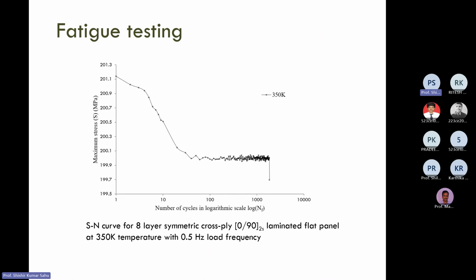This is the fatigue testing. We have done the fatigue testing. You can see the SN curve for an 8-layer symmetric cross-ply laminated flat panel at 350 Kelvin with 0.5 Hz load frequency. Our machine has a capacity of up to 5 Hz. So we give both dynamic load and static load, and the fatigue behavior has been studied.